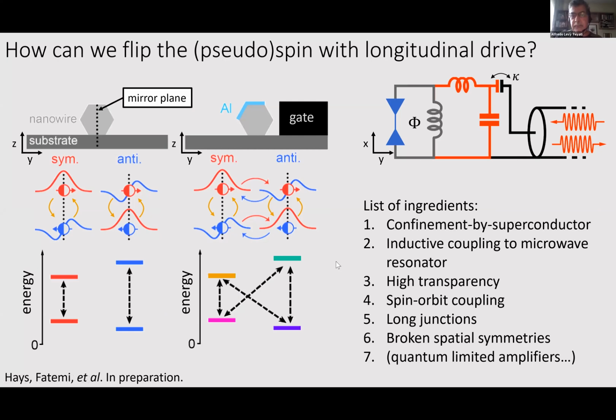Maybe I'll comment that the breaking of the spin conservation is also more likely if you are closer to a higher subband. That's why maybe when you change the gate voltage, you come closer to a higher subband. So what Alfredo is talking about is that basically these yellow arrows don't show up if you're not close enough to a second subband of the nanowire, to the asymmetric band. So you might expect that at higher gate voltages, this entanglement between spin and orbital is stronger, and therefore the mirror symmetry can break things more easily, can break the selection rule. This is actually also a given, though, that we need this entanglement to get the velocity asymmetry in the first place that lets us split the spins.